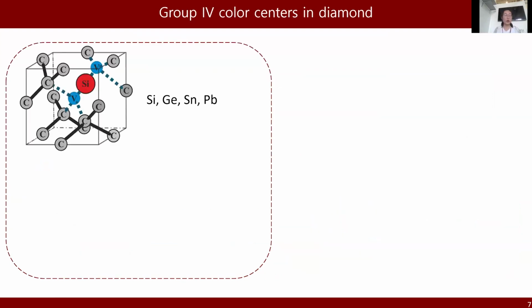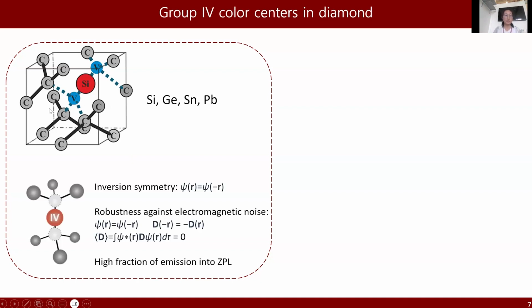So now I want to give a brief introduction to group 4 color centers in diamond, including the germanium vacancy center. A group 4 color center consists of a group 4 atom sitting in the center of 2 neighboring carbon vacancies. And this group 4 atom could be silicon, germanium, tin, or lead. If we take a closer look at this molecular structure, we can see that these group 4 color centers have so-called inversion symmetry, which means that if we invert the position, the electron wave function will stay the same.